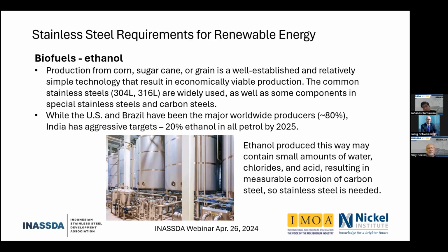So ethanol produced in this way from the corn, sugar cane, or grains contains a small amount of water, chlorides, and acid, and it results in a measurable corrosion of carbon steel, so stainless steel is needed. When I visited a bioethanol plant here in North America, I met the maintenance person there, and she said that her plant was basically 80% stainless steel, but she wished it was actually 100% stainless steel, because the only maintenance they do at that time was on the carbon steel, replacing it on a fairly regular basis. So it is good to try to optimize by using stainless steel 304, 316 in these plants.